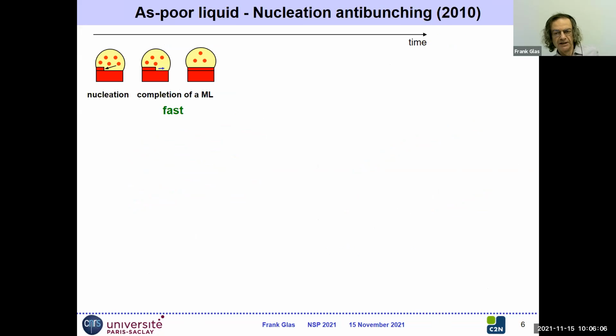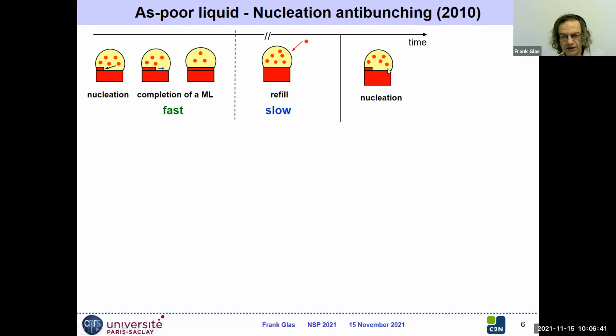Now, this brought us to the idea we had about 10 years ago about the formation of an individual monolayer. It starts with nucleation of a 2D nucleus. And then, because we have overcome this nucleation barrier, we expected the formation and the completion of the monolayer to be very fast, simply using the arsenic atoms which were stored in the droplet. Then, after we have done this, we expected that we had to wait for some time because the droplet has to be refilled, and then we might have another nucleation event and another monolayer forming.